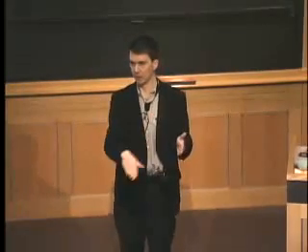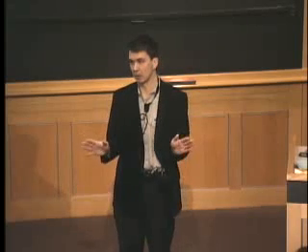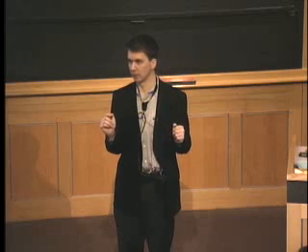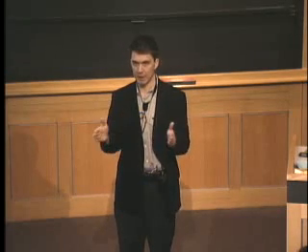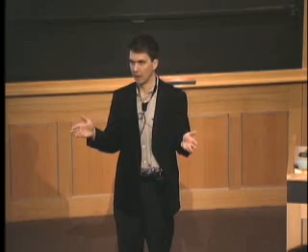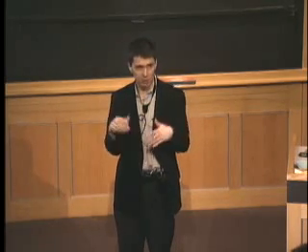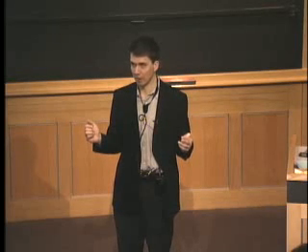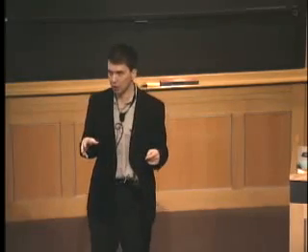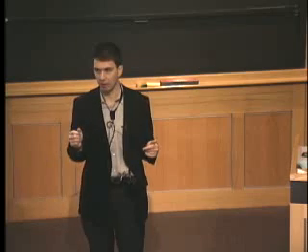I could literally do ab initio calculations at different lattice parameters, and that would give me a curve, energy versus lattice parameter. I could fit my potential to that. If I do that, I have never included any polarization effects. Because at every lattice parameter, that is still a high symmetry state. At none of these lattice parameters is any of the ions ever polarized. Does it ever have a dipole moment on it? And so what you see is when you go and do defect calculations with that potential, you will almost always overestimate their energy.